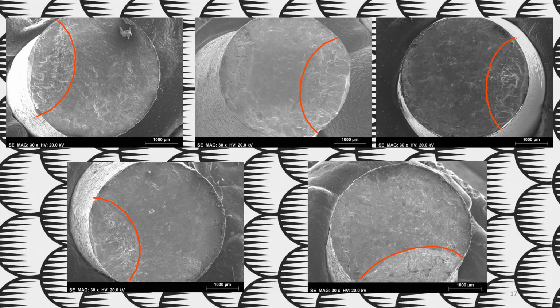This behavior was observed in all tested specimens, from as-built to polished specimens, where we have surface to subsurface crack initiation, a propagation following the curvature similar to the previously published results, which changes in curvature, associated with a higher surface propagation, until the total failure of the specimen.